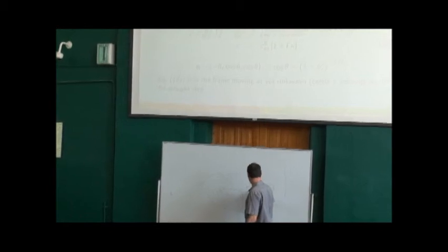So on this lower terrace, you have the static diffusion equation, all right? Where at infinity is over here, the step is assumed infinitely long. At infinity, you fix the concentration field, all right? And the physical value of concentration there is the product of tau times F. So at infinity on the lower terrace, the concentration is fixed.